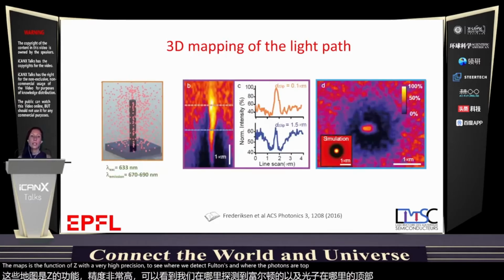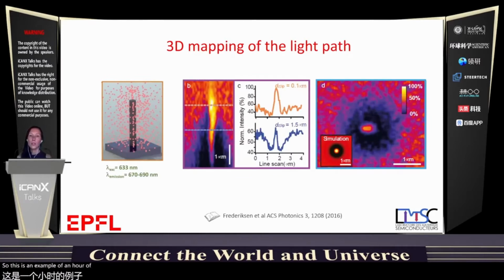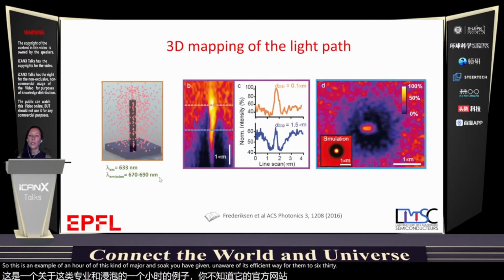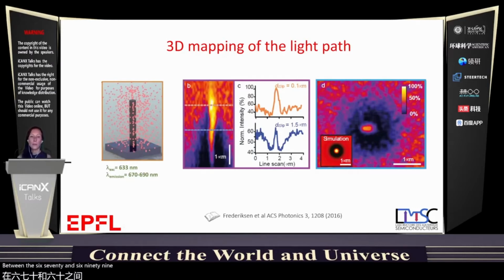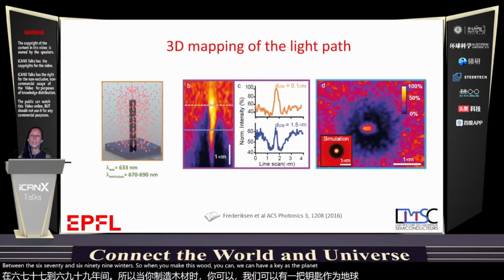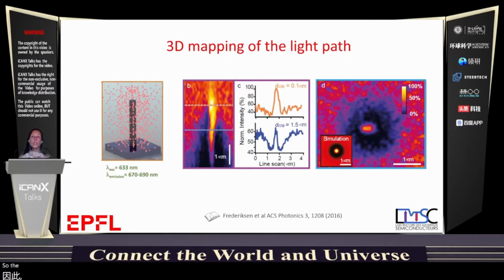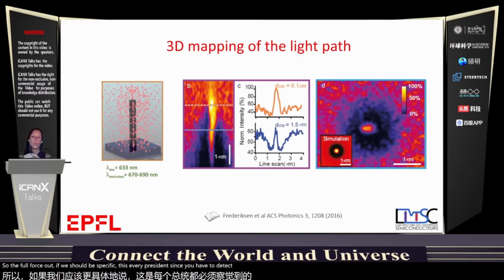So this is an example of this kind of measurement. So you have here the nanowire, the excitation wavelength is 633, and the detection is between 670 and 690 nanometers. So when you make this, we can have here a z-plane in which we see how, very far from the wire, you have homogeneous light emission. So the fluorophores are homogeneously distributed everywhere, and so you detect photons independently of the z space.